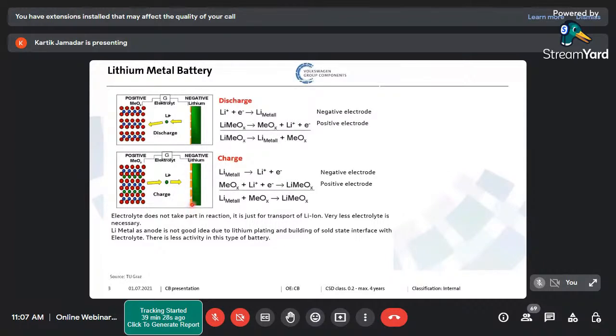They were basically forming the dendrites. So you would imagine that there were some peaks and valleys, and that the peaks would keep on increasing. And we know there is a separator in between. The separator is such that the ions can move through it, but electrons cannot. Now, if the dendrites keep on increasing, they would eventually penetrate the separator and touch the cathode. And then we get a short circuit.